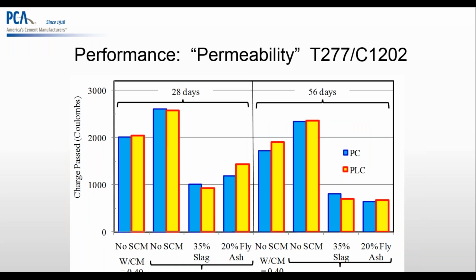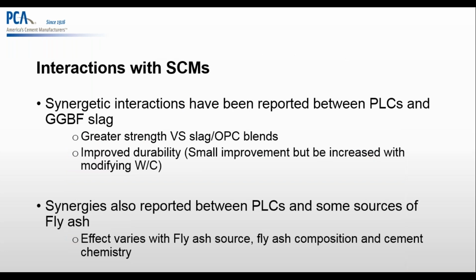At later days, 28 and 56 days, looking at an important test, which is the RCPT, the permeability test, the C1202, you're looking at equivalent performance here, whether you're using a water cement ratio of 0.40 or 0.45, with or without slag. And of course, the addition of SCMs will improve the performance of your PLCs.